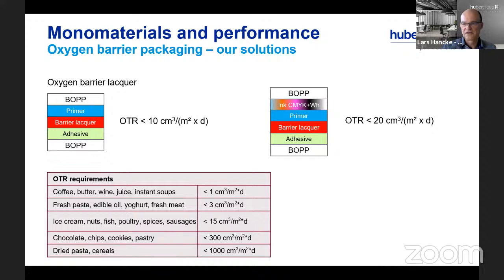So whether you work in Flexo, this is more or less the Flexo figures, because our partner from the industrial side, from the converting side, with whom we developed this system, is a Flexo printer. If you apply more in gravure, if you combine, for instance, also with metallized films, then you get even in the range of oxygen transfer below one. So at least we can cover here the medium complexity requirements heading for the more demanding application with our system.